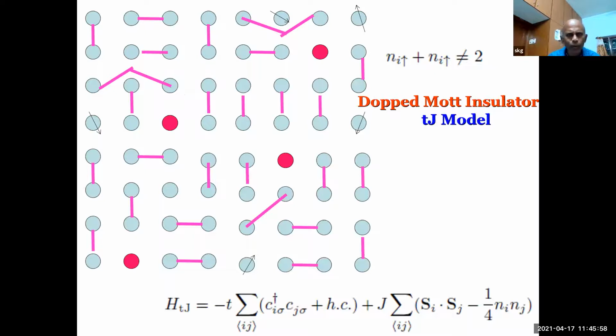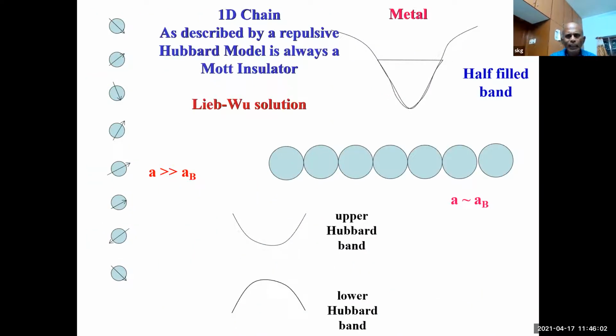Now, what I knew and many people knew was that something very strange happens with respect to, for example, silver or gold wire. Suppose I take a silver or gold wire and describe it by a Hubbard model and solve it. Lieb and Wu, my friend Lieb, has solved it exactly for us. You find that silver chain or gold chain, because of lower dimensionality, always remains Mott insulating, which also says that there is a lot of super exchange physics. There is a lot of singlet pairing. And then if you estimate the singlet exchange coupling J, it is like 1.5 electron volt, embarrassingly high, 10 times higher than cuprate. That means silver or gold, if you can prepare them in good lower dimensional form, they will support a lot of RVB physics.